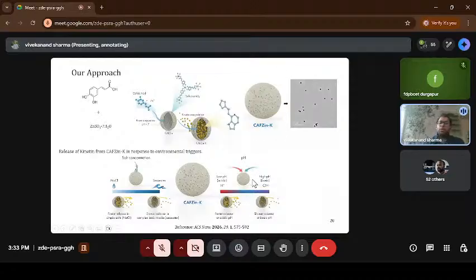When we studied this, we found that this formulation releases kinetin slowly over a certain time when irrigated with water, like seawater. In a similar way, we also studied the effect of pH on kinetin release. We found faster release at low pH, when the surrounding medium is acidic, the network releases kinetin faster. But when the pH is basic, the formulation releases kinetin very, very slowly. This is going to help a lot because in India, the soil pH varies from region to region. Some is acidic and some has basic pH.